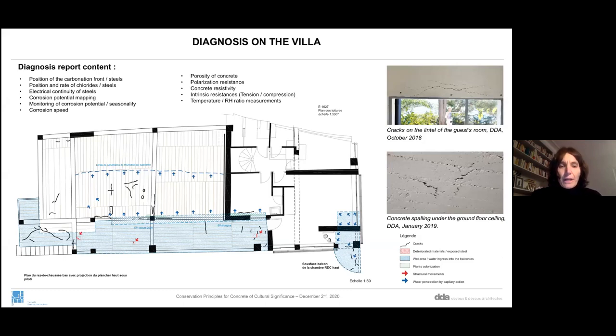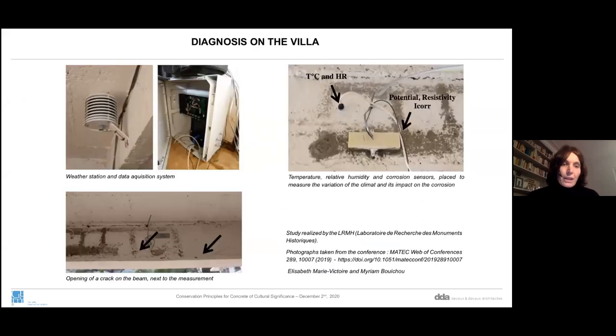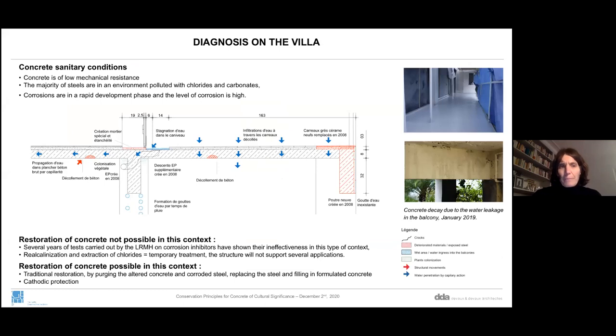And you see on the picture here, the main problem was that the balcony was not waterproofed, and water spread out in the whole ceiling and the pillars, and made the concrete very carbonated and in a very bad condition. We installed a weather station where we measured the temperature, the relative humidity, and the corrosion activity during nearly 2 years. And we found out that the concrete sanitary condition was very, very poor. The majority of steels were in a polluted environment with chlorides and carbonates, and the corrosion of the steel was very active and very high.